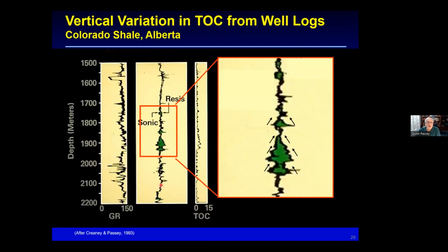Now, the field work. When we developed this, again, it was a very fast technique, and it's been applied since the 80s. We applied it to thousands of wells. We'd see someone's publication, we'd go in, we could digitize the logs off their publication, and we could do a DlogR overlay. But this is from Cretaceous age Colorado shale, Second White Specks. In Canada, it's being looked at as unconventional. But when we look at the overlay, it looks like a pine tree. And we kept seeing this, high TOC decreasing, high TOC decreasing, high TOC decreasing. And we were really wondering what is going on with this.